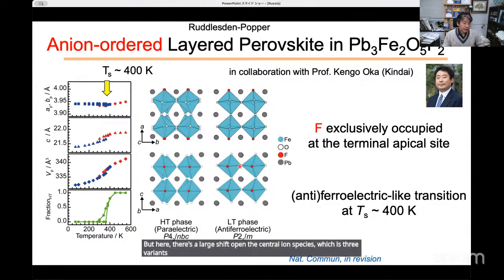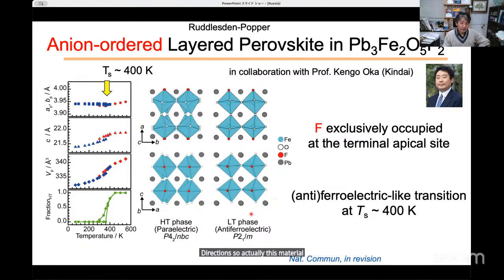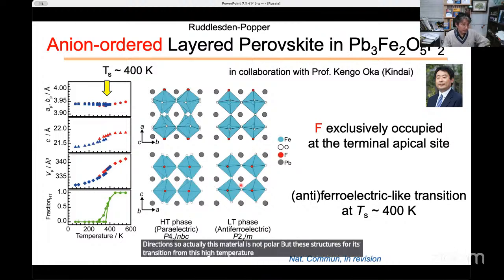But a large shift is a signature of the ferroelectric transitions. In fact, each layer is ferroelectric, with polar structures. But neighboring layers have different polar directions. So actually, this material is not polar. But this structure phase transition from this high temperature phase to low temperature phase is similar to the transition you can see in, like, lead titanate or maybe barium titanate oxide. Okay. So structure phase transition occurs.